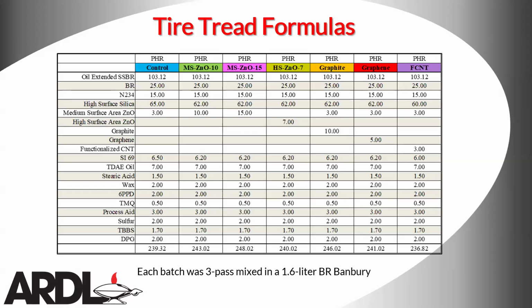First of all, these are the formulas that we ran, and this is just a very standard passenger tire tread formula. You can see that our main filler here is our silica with 15 parts of carbon black. What we did is we replaced low levels of the silica with a more thermally conductive filler. We replaced 3 parts of silica with 7 parts of a standard zinc oxide, because in our control we had 3, so we moved up to 10. Then we actually increased the level up to 15 parts.